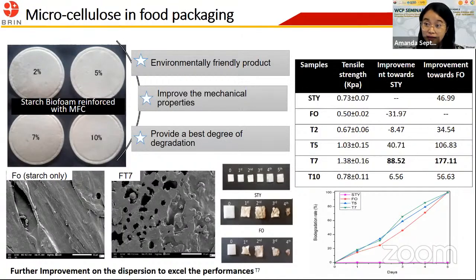In terms of biodegradability, it can also be degraded in a very short time, within 5 days, by just burying our foams in the soil. But we still have some challenges. For example, when you see this morphology, once we introduce our microfiber cellulose, there are big voids or this disturbed morphology. We will do further improvement in terms of dispersion technology, as well as by introducing the nanofillers itself. And we believe that this dispersion may further improve the performance of our biofoams.